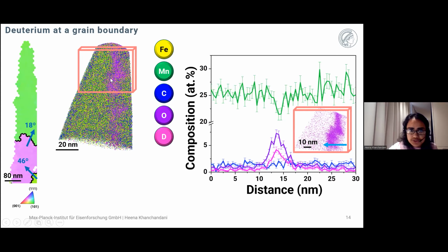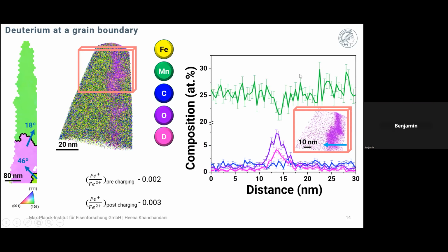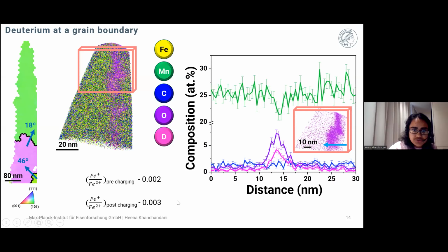Now here there were 2 grain boundaries and both of them were faceted. So I'm showing the composition profile across one of the facets, in which we had the enrichment of deuterium and oxygen with the depletion of manganese. And we have the pre and the post charging data to compare the field evaporation conditions of the analysis, for which we use the charge state ratios as a proxy, and which shows that the field evaporation conditions were uniform for both analyses.